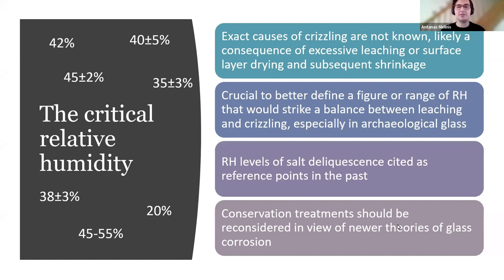And we don't fully know what sets it off. It's probably some sort of physical difference between the parent glass and the hydrated layer, or within the hydrated layer itself, but some sort of internal stresses that cause it to collapse. Either when the alkali are leached out to the degree where the structure of the glass collapses on itself because of the voids, or when it swells because of the water entering its structure and again cracks up.